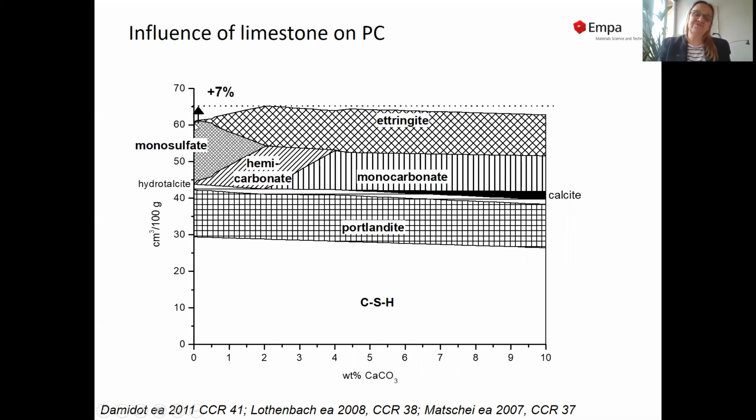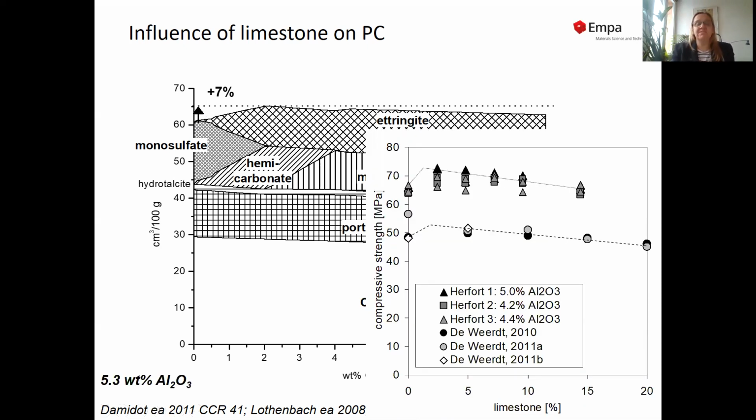This stabilization of ettringite leads to an increase of the total volume of the hydrates. And this is important because we can see this increase also mirrored in an increase in compressive strength in mortar samples after 28 days and 91 days.